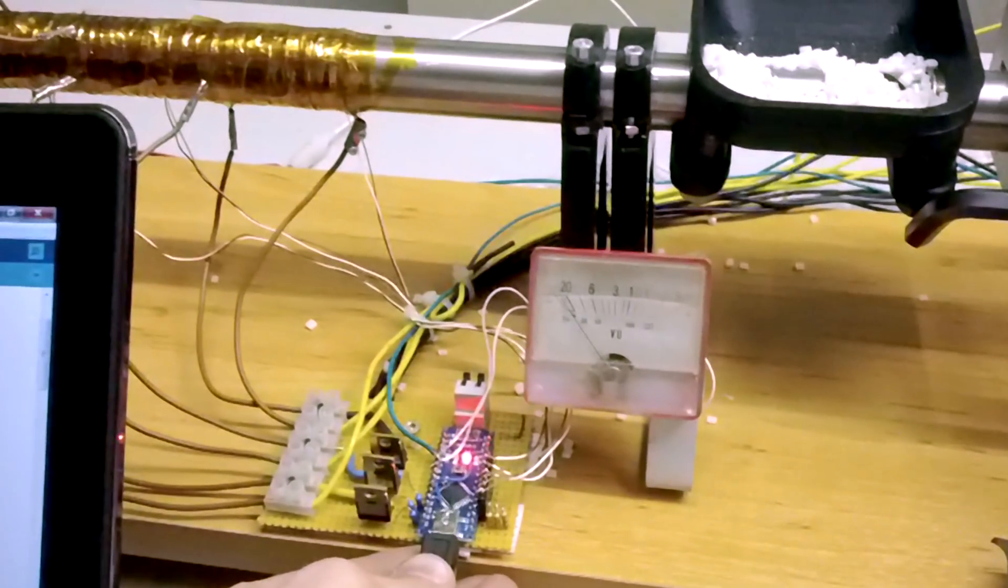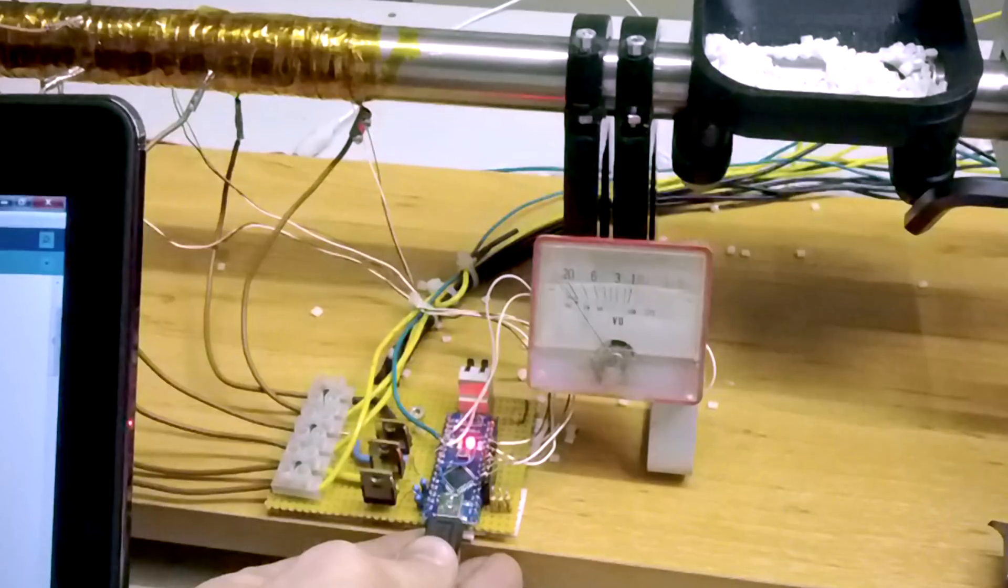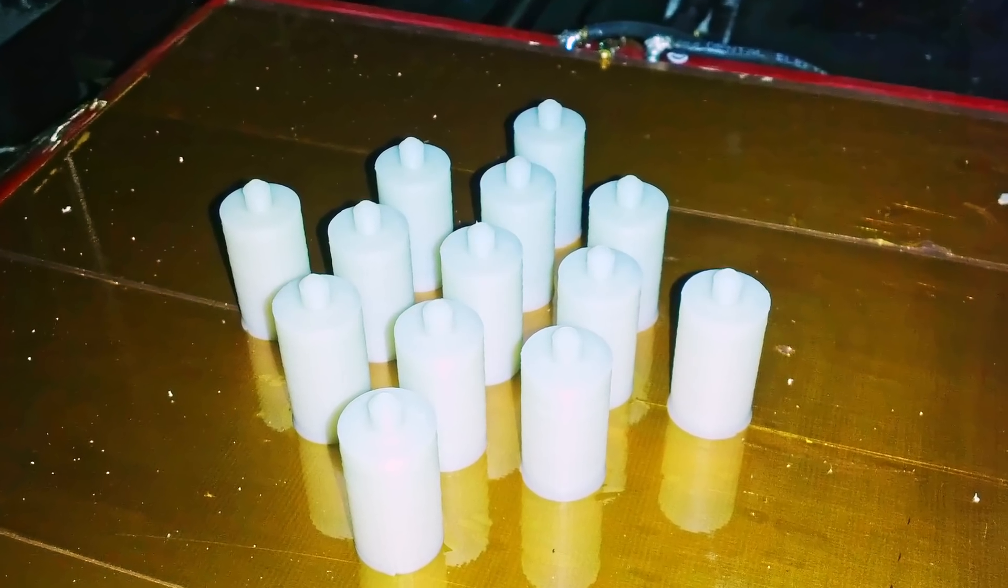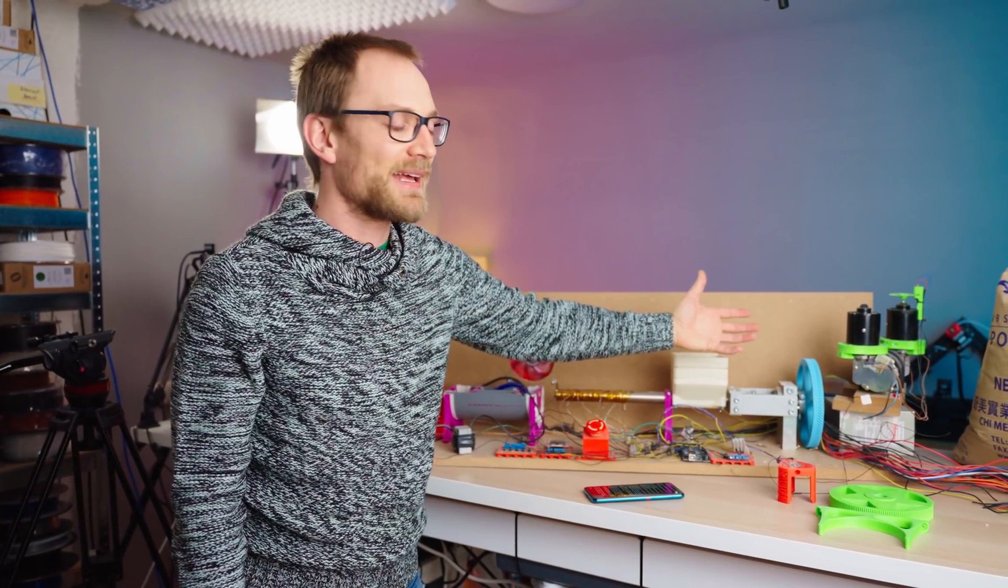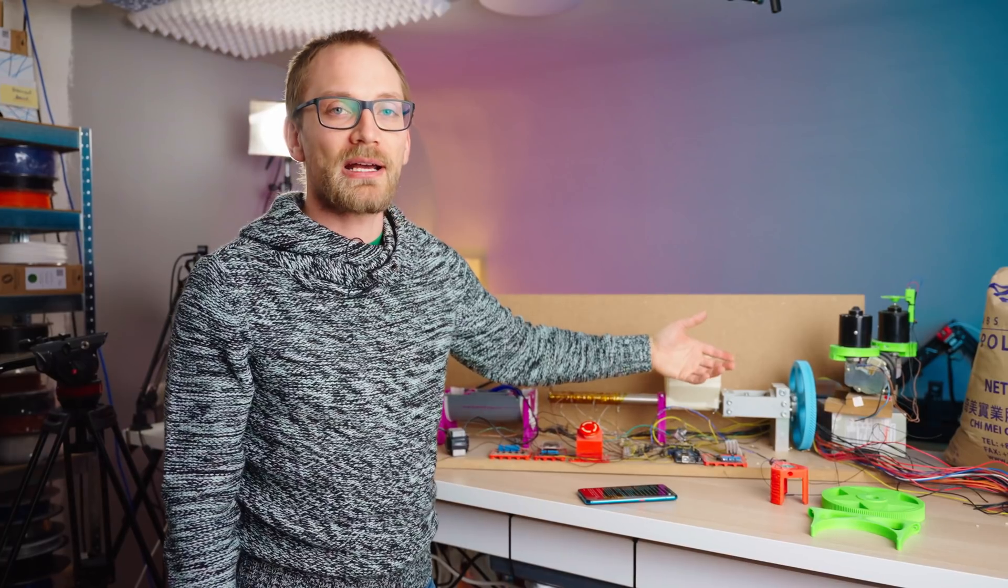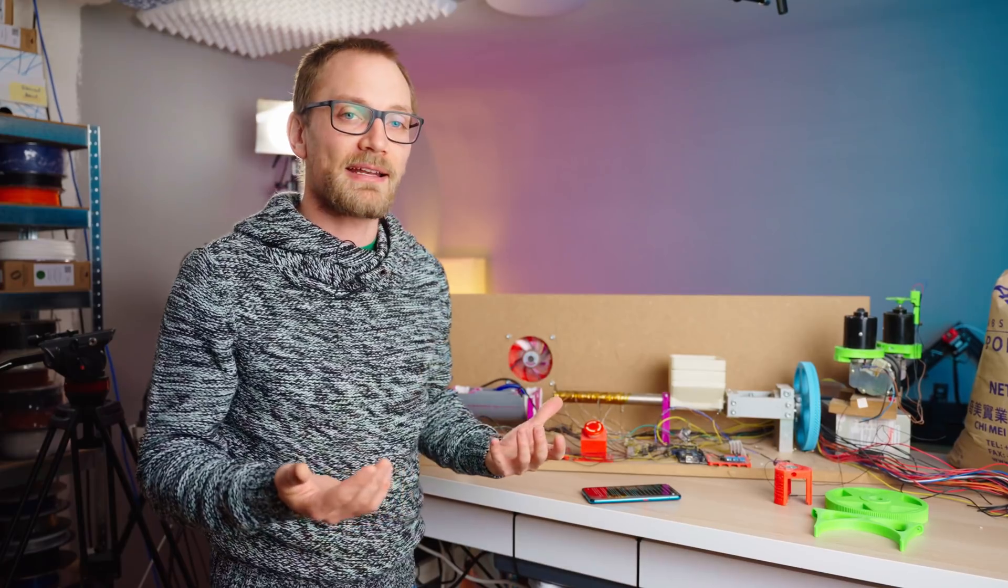And that was actually the solution that got me some filament that was very usable. I got a couple meters of fairly accurate 3mm ABS filament out of it and it did print. This Polylac 747S prints like a dream. The only problem was the drive unit didn't last too long and started burning up, started smoking, so I stopped that extrusion. But I had made some filament that was very, very usable and actually better than I was hoping for.